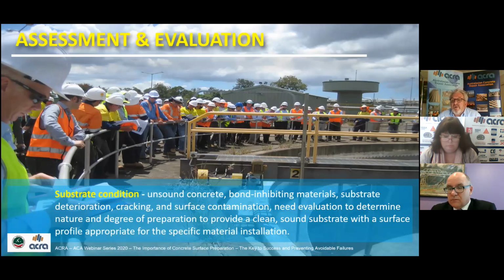The assessment and evaluation, we've got to look at the substrate condition. The substrate, including presence of unsound concrete, bond-inhibiting materials, deterioration, cracking, surface contamination. It all needs to be put into the package to evaluate and determine the nature and the degree of the surface preparation required. The preparation must provide a clean, sound substrate, with a surface profile appropriate for the specific material installation.